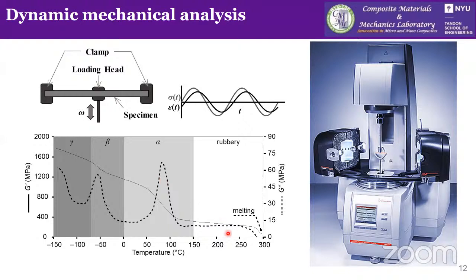So this is also the best method to measure the glass transition temperature. It is better than DSC because you can see these sharp peaks in loss modulus. The temperature of this sharp peak is actually the glass transition temperature. And then there are these different temperatures of alpha, beta, and gamma transitions, which can be measured from the same experiment. Now, for this particular material, if you conduct the experiment from room temperature, which is about 30 degrees C, to high temperature, you will capture only one peak, which is the glass transition temperature. But if these experiments were conducted from minus 150 to about 250 degrees C, then you'll capture these additional peaks for thermal transitions in the material system.